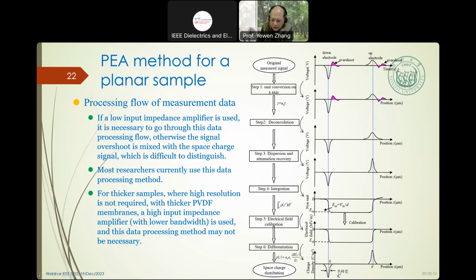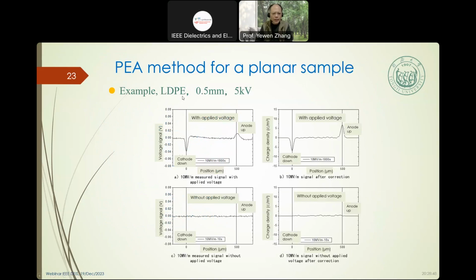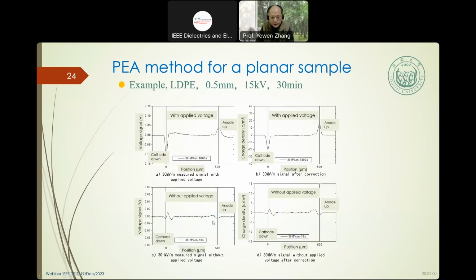Sorry, this is in Chinese. This is very similar to the thickness of the PVDF film. So, for example, for LDPE of 0.5 millimeter with a 5 kV applied voltage, we can get the low field, so we get signal without space charge. After some time, we apply 15 kV. After 30 minutes, we get the space charge like this without applied voltage. So we know this one.